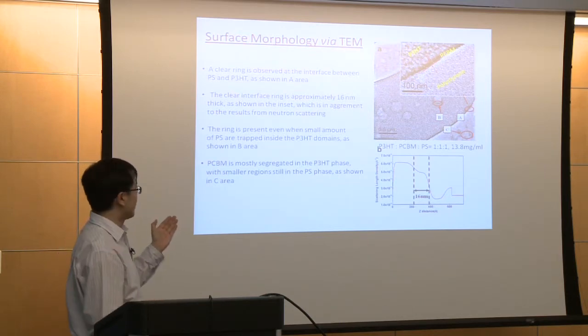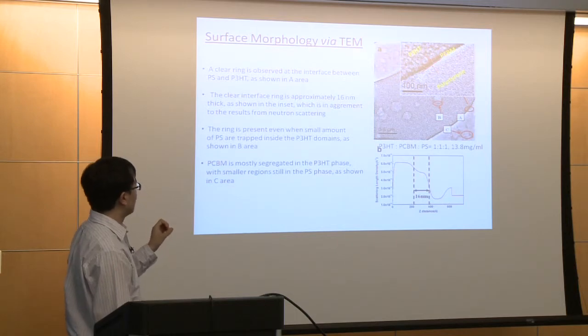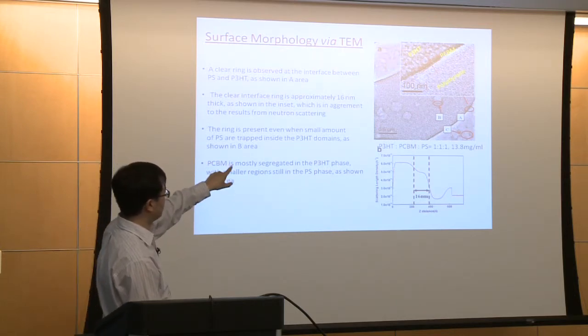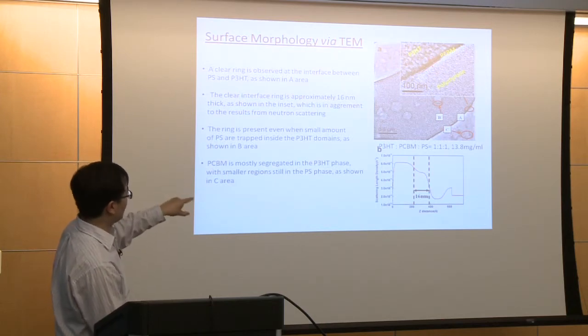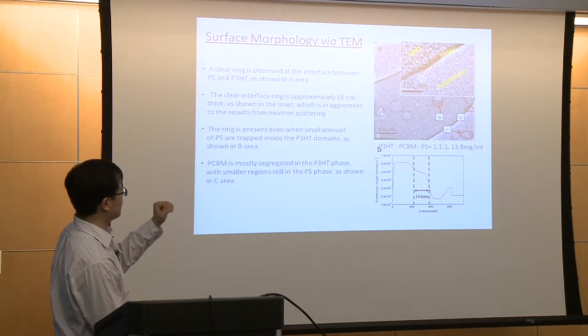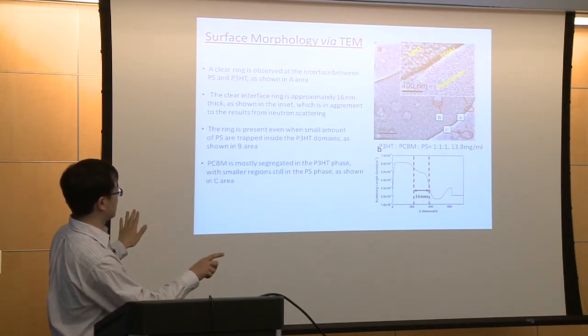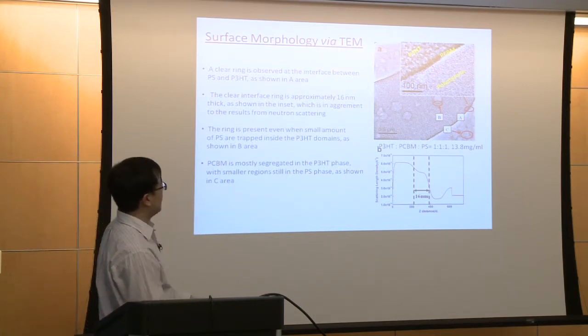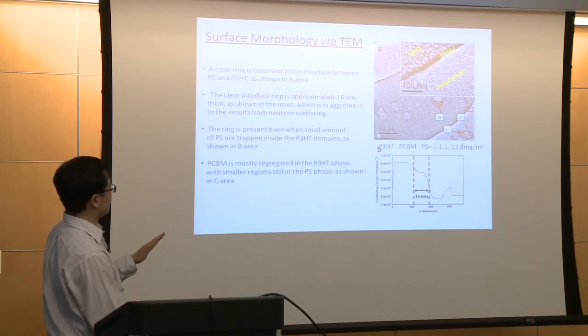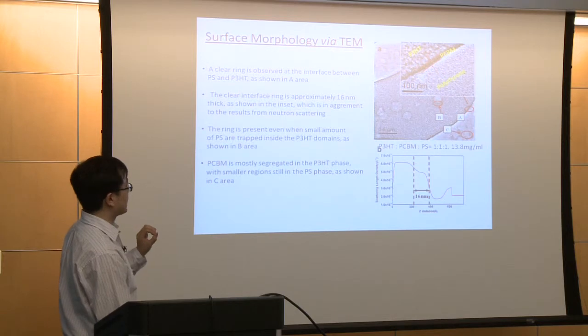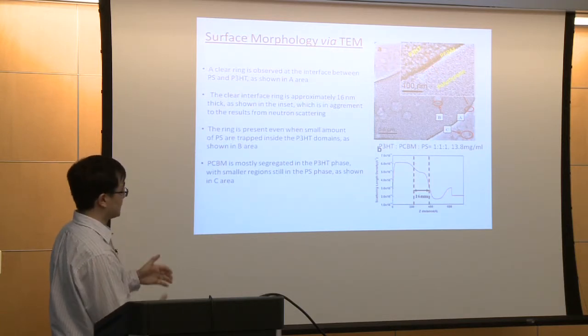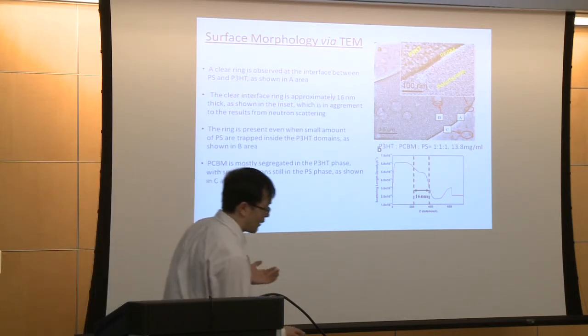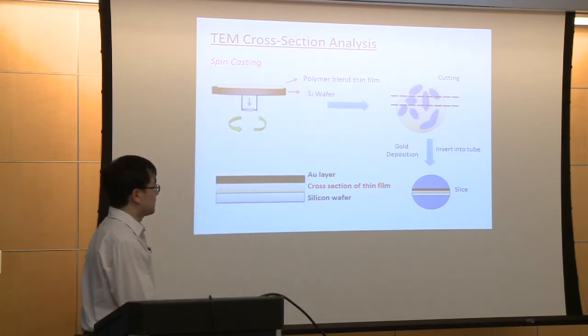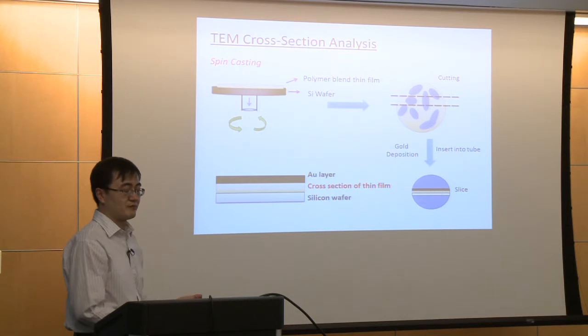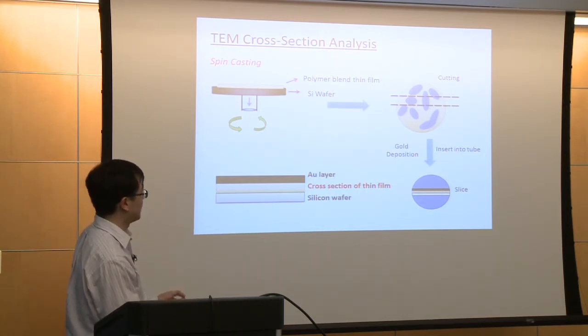And you may also notice that the ring is present when a small amount of polystyrene is trapped in the P3HT phase. You can see many small rings inside that big domain. The dark ring around that small domain is actually PCBM, and inside is polystyrene trapped in the P3HT, and the other phases are just P3HT. Okay, and if you take a look at the C area, maybe not that clear, but still you can see some dark phases there. So actually there's still some PCBM trapped in the polystyrene phases. Although they don't like each other, sometimes it's not up to them. So in this way, we confirm the segregation of PCBM at the interface between polystyrene and the P3HT.